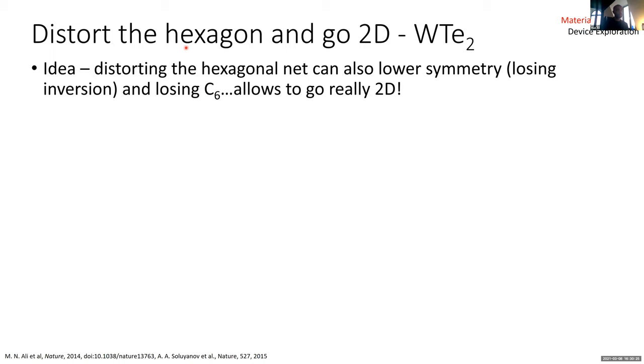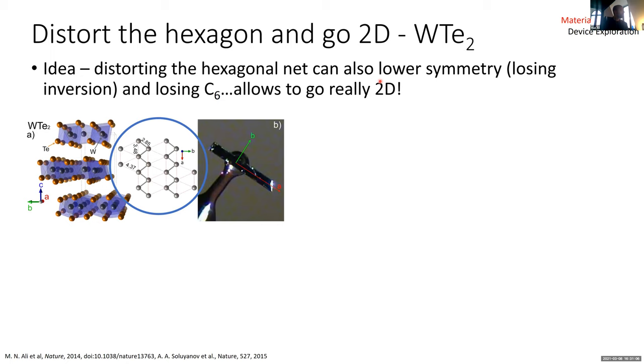So I went combing through the transition metal dichalcogenides, since that's where I was living at the time, in my head, I guess. And interestingly, there were two known materials to satisfy that request of breaking the hexagon while maintaining the 2D van der Waals gap layered symmetry. And in the TMDs, the only two materials that were known to do that at the time were tungsten ditelluride and its sister, molybdenum ditelluride. And only tungsten ditelluride was expected to be the stable ground state. So we went ahead and made it. And this is what it looks like. And so this is how the hexagon cracks.